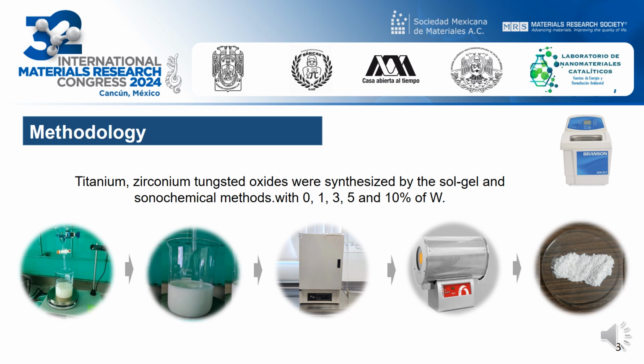A second drying was carried out. The material was annealed at 500 degrees in a tubular furnace under an air atmosphere for 12 hours with a heating ramp of 2 degrees per minute in order to eliminate organic and inorganic impurities from the material. Then the materials were annealed at 650, 700, and 800 degrees respectively in order to study the phase transformation.